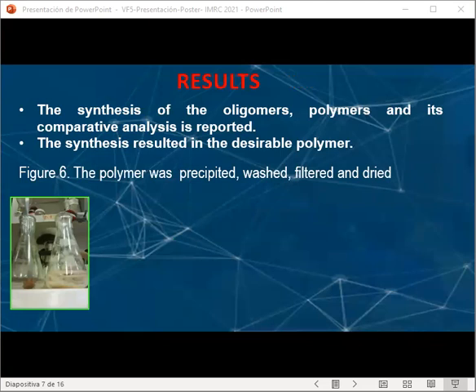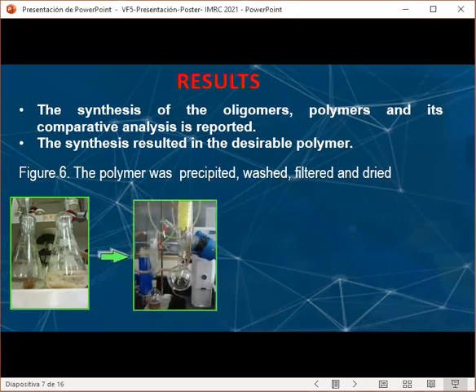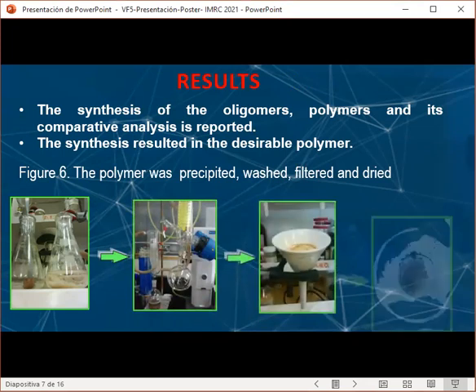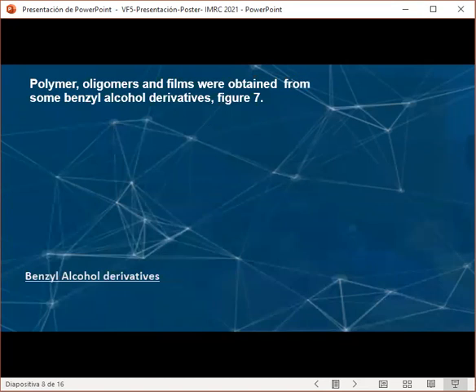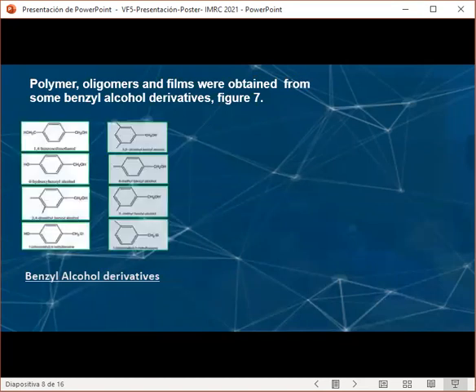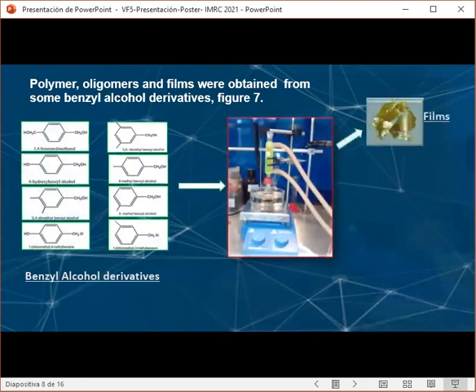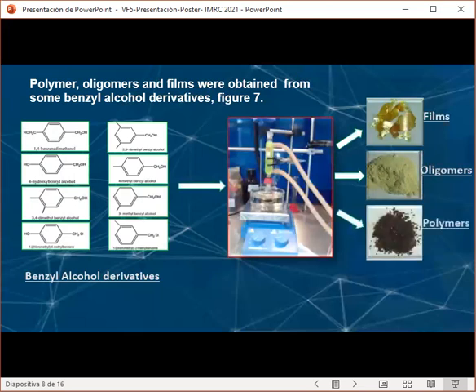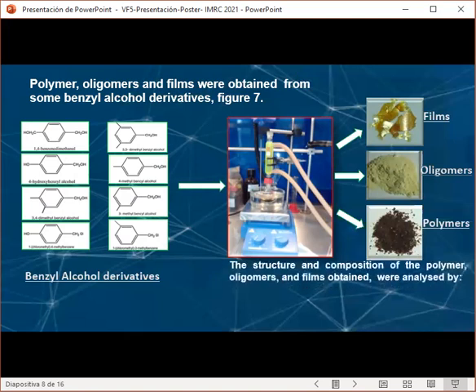The synthesis of oligomers and polymers, and their comparative analysis, is reported. The synthesis results in the desirable polymer. You can see it in Figure 6. The polymer was first precipitated, then washed, then filtered, and finally dried. The structure and composition of the polymers, oligomers, and the films obtained from some benzyl alcohol derivatives are shown in Figure 7. They were analyzed by X-ray diffraction, infrared, NMR, TGA, DSC, and AFM.